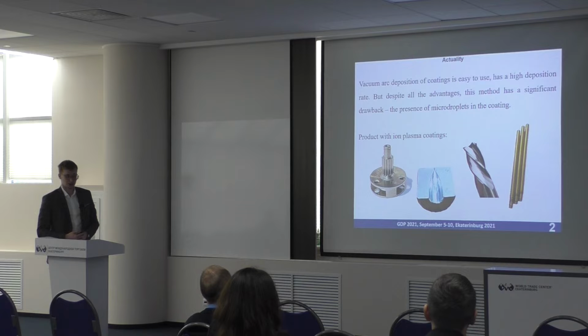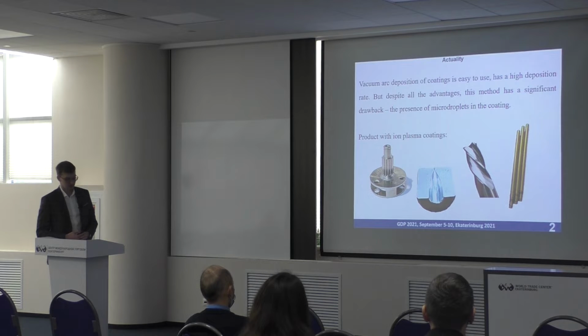In vacuum arc deposition, a jet of cathode vapor plasma is formed by the vigorous evaporation of the cathode material. In addition, the arc discharge also produces small liquid droplets, commonly referred to as macroparticles or microdroplets. The evaporated cathode material is deposited on any substrate intercepting part of the jet, forming metallic or semiconductor coatings, depending on the cathode material.